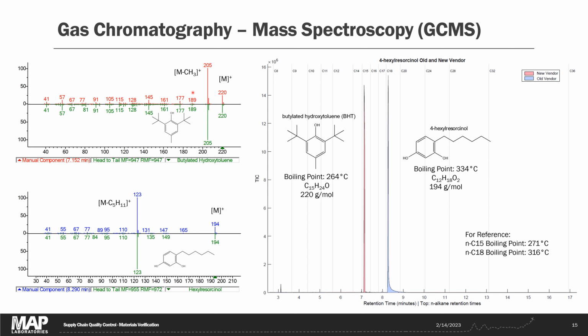Over here we have the fragments seen by the mass spectrometer. For BHT, we saw 220, which is the molecular weight of this molecule. You've got carbon, which is 12 times 15, hydrogen, which is 1 times 24, and oxygen, which has a molar mass of 16. Add that up, you get 220. This 205 is basically this molecule minus a CH3 group.